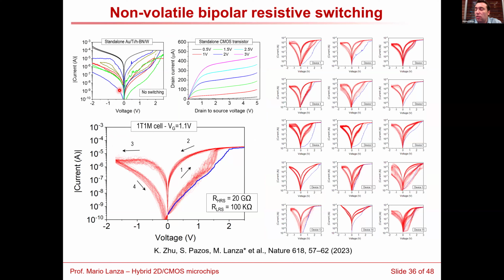Then we measure the standalone device without any transistor. We observe random fluctuations on the conductivity, but there is no reproducible switching. And if we increase the voltage beyond 2.5 volts, basically what we see is that the device melts, okay? There is no current limitation. So basically, this device is so small that it probably contains a low amount of defects, and the energy to break down is higher, and therefore this thing melts. When we measure the standalone CMOS transistor, it works as expected, as it should. Like one transistor, there is no secret here.